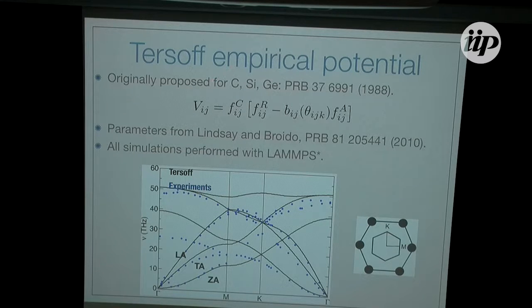The Tersoff potential was originally proposed for carbon, silicon, and germanium systems in a series of PRB and PRL papers around '88, '89. It has this general form here. You have a repulsive term. You have an attractive term. You have a term that involves the angle between three atoms. And you have a cutoff function to make sure that the one atom that is here doesn't interact with atoms that are very far from it.